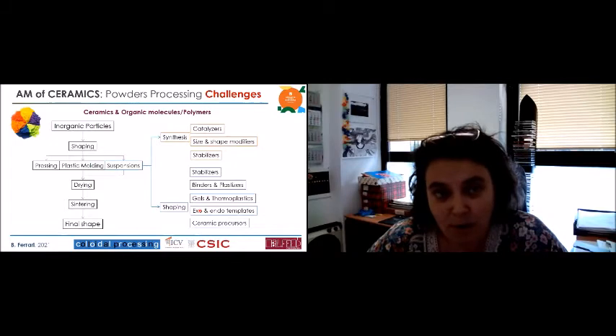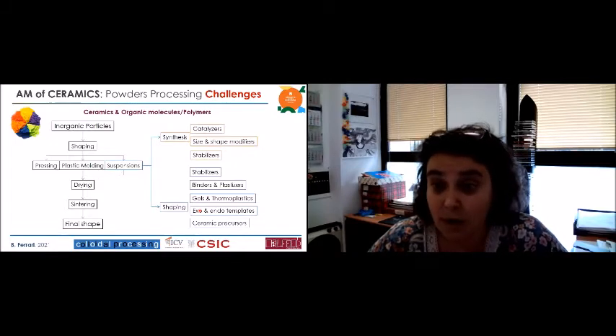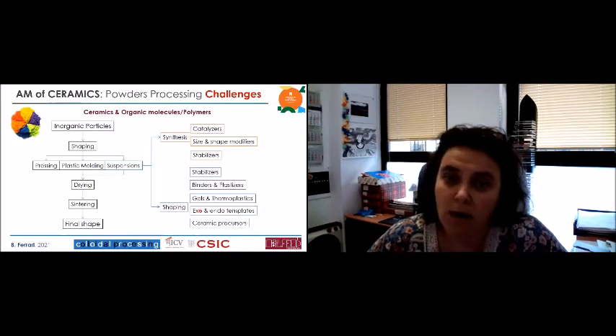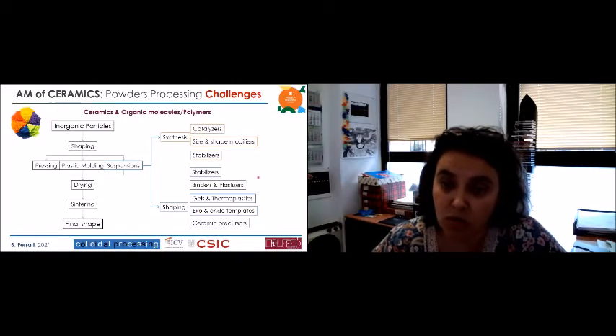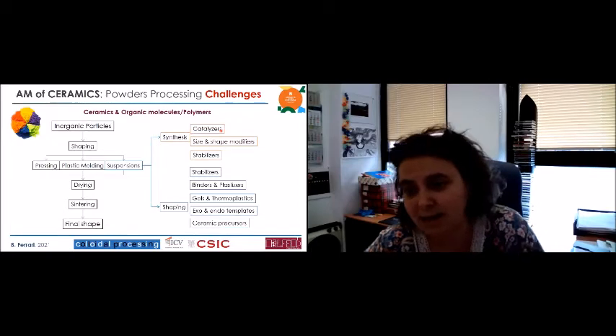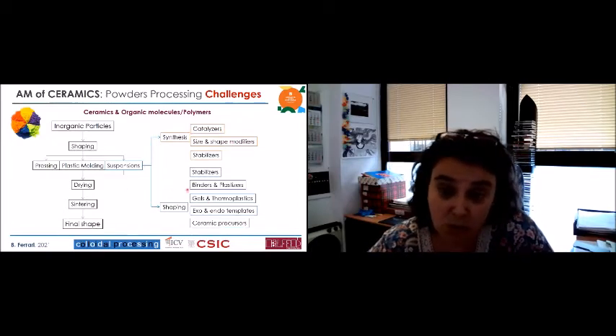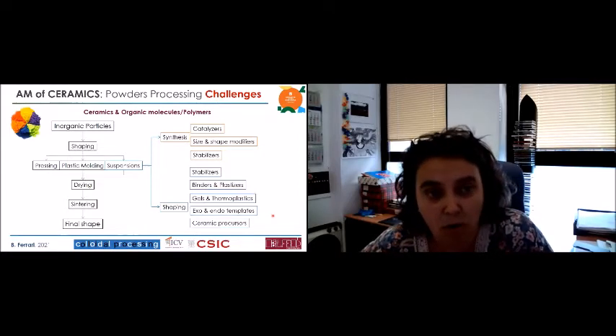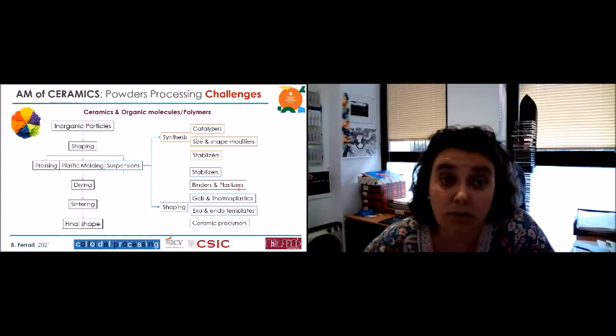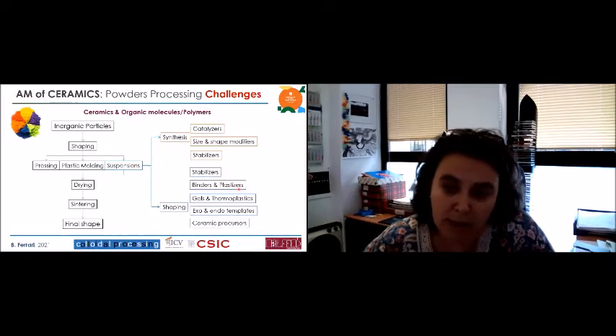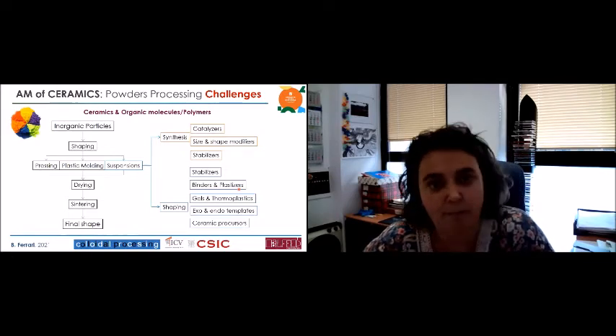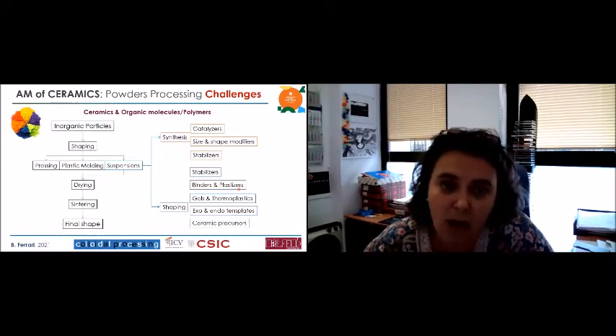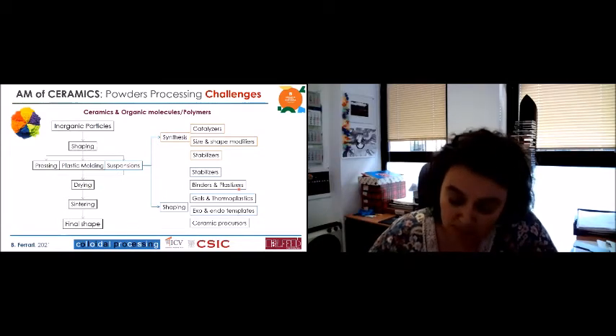Really, organic molecules and polymers have been in the life of ceramics for a long time. And right now we are using more and more organic molecules and polymers in all the steps of the production of ceramic material, right? For synthesis, we use catalyzers, size modifiers, and stabilizers. But to adjust rheology and to produce material, we also use binders and plasticizers, gels, templates, or ceramic precursors. So all these polymers are very important raw material for additive manufacturing in ceramics, because if we don't have them, we are not going to produce the ceramic correctly, and we are not going to achieve dense and compact material at the end of the thermal process.